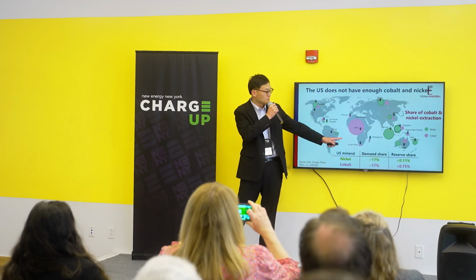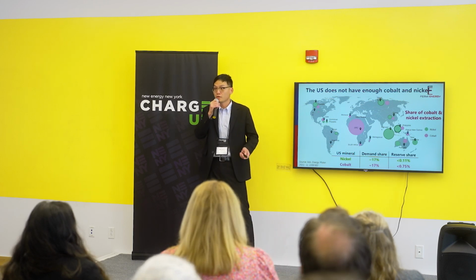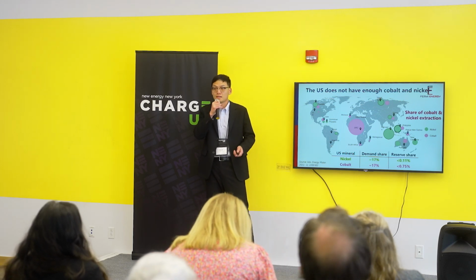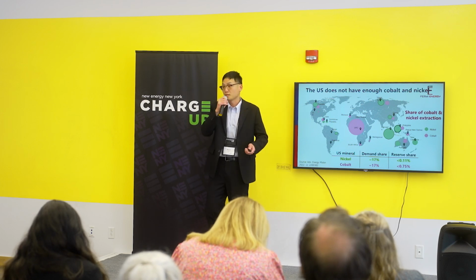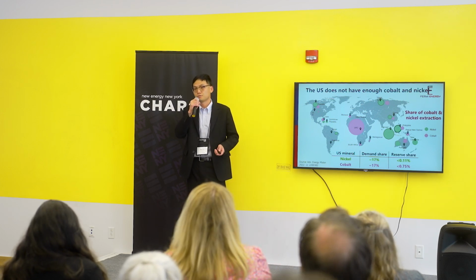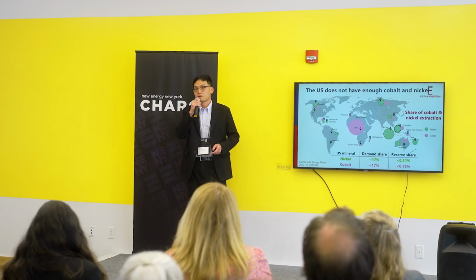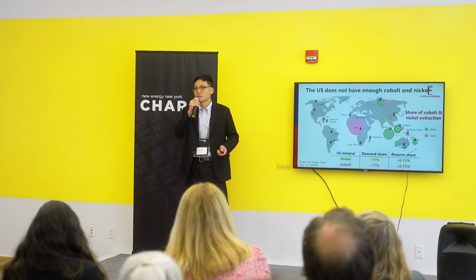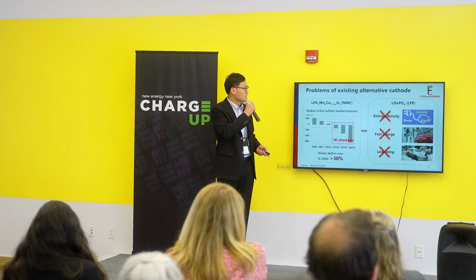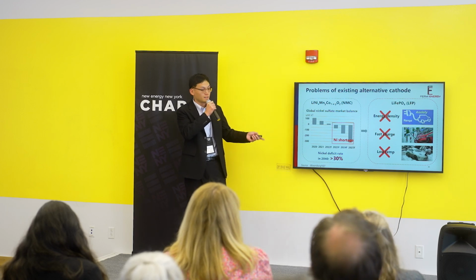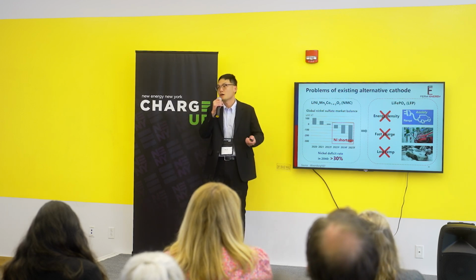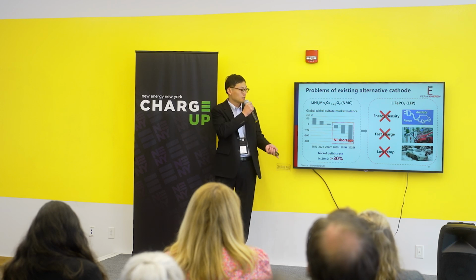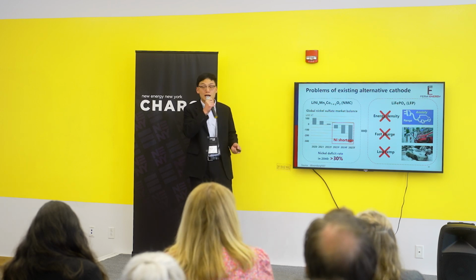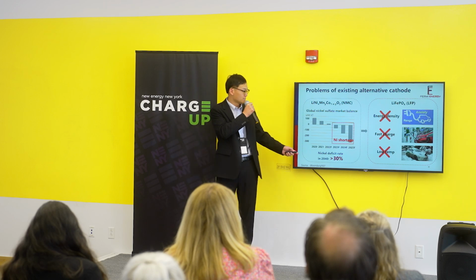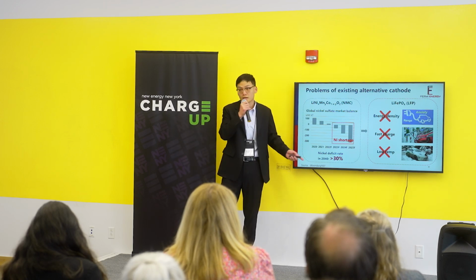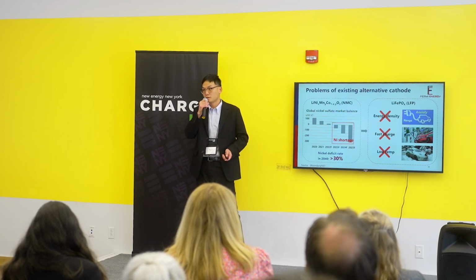The percentages for nickel is less than 0.11%, and cobalt is less than 0.75%. And that's why the US DOE has laid the goal to eliminate both of the minerals from the next generation batteries by 2030. Globally, we already see this nickel shortage because there's more adoption of EVs and the nickel consumption rate is skyrocketing these days. Based on a Bloomberg report, by 2040, the nickel deficit rate will be more than 30%.